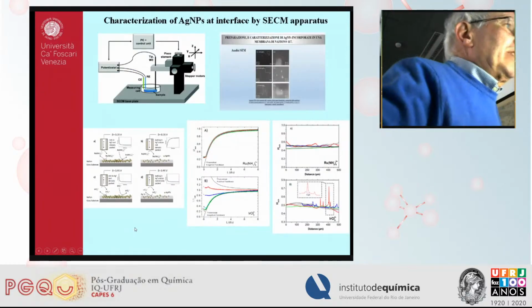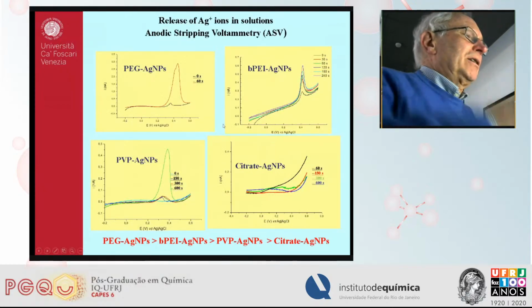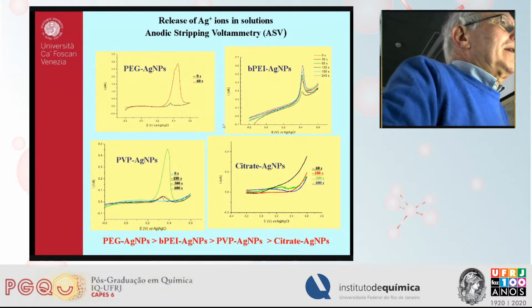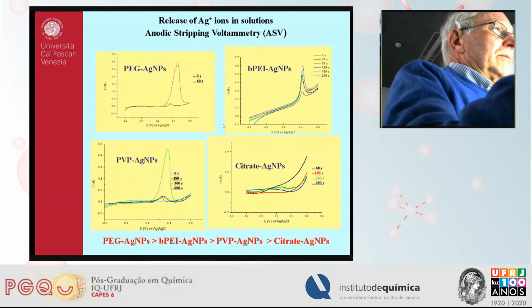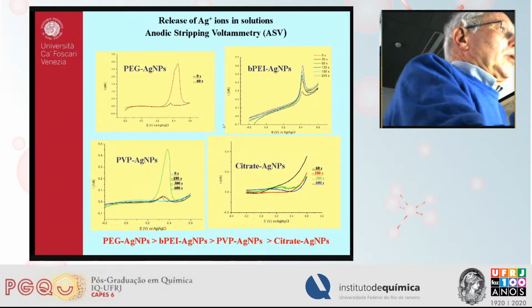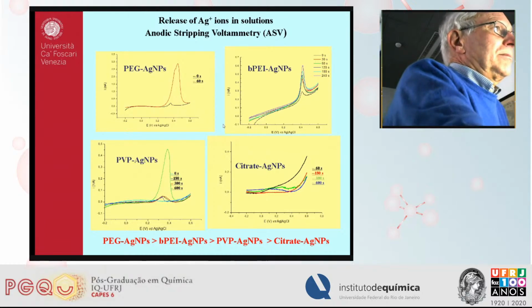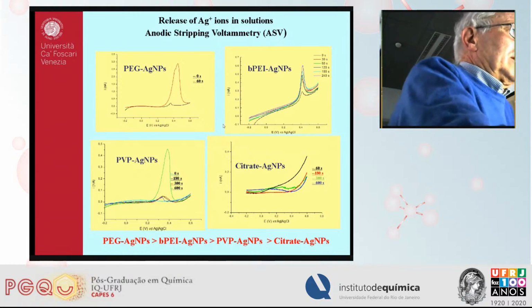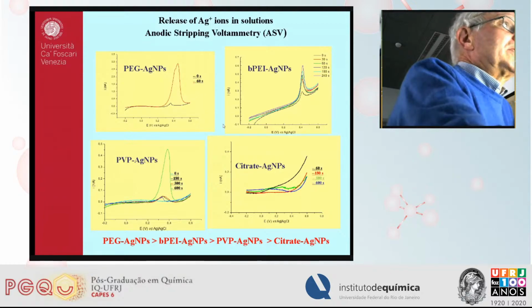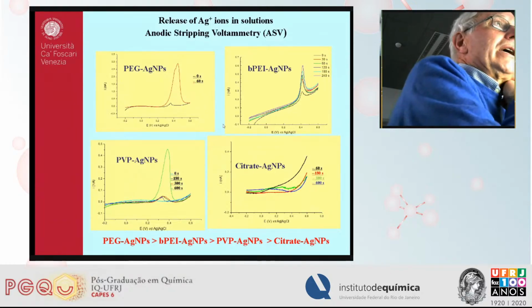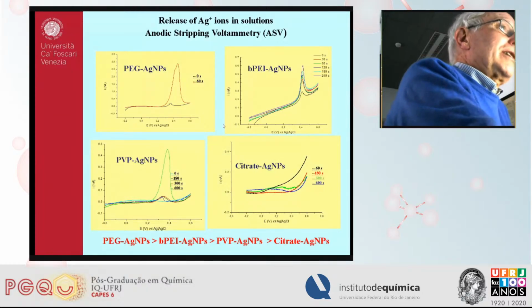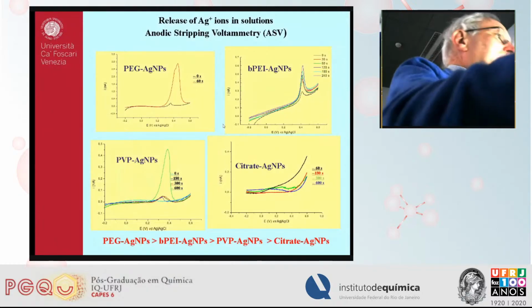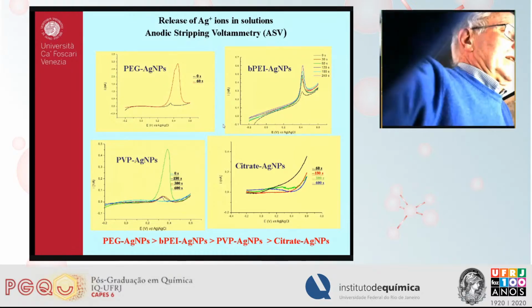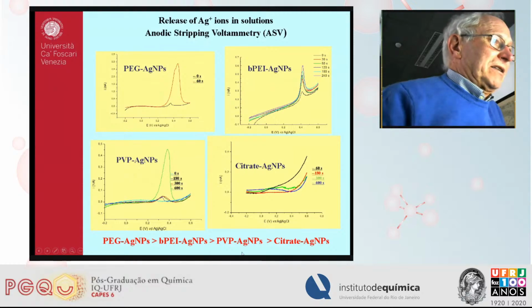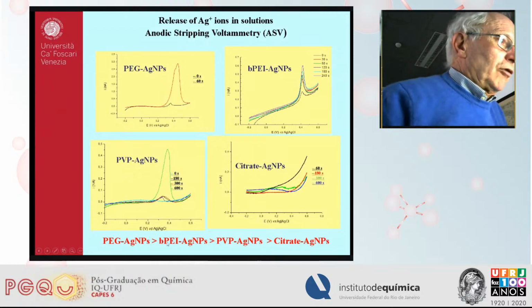The measurements I showed before were performed by obtaining a suspension of these nanoparticles in the medium. The medium in this case was water, but we did the same investigation using food simulants. Food simulants for liquid foods are, for instance, water and ethanol mixtures. So we made the same measurement in these media, and we could establish the reactivity of this system in the other media. They provide almost a similar order of reactivity.